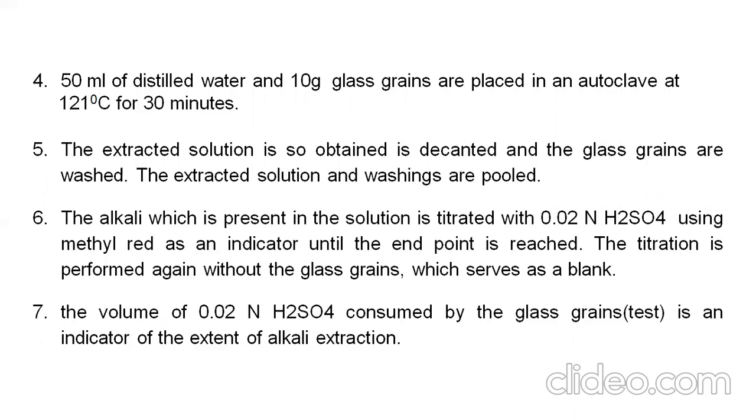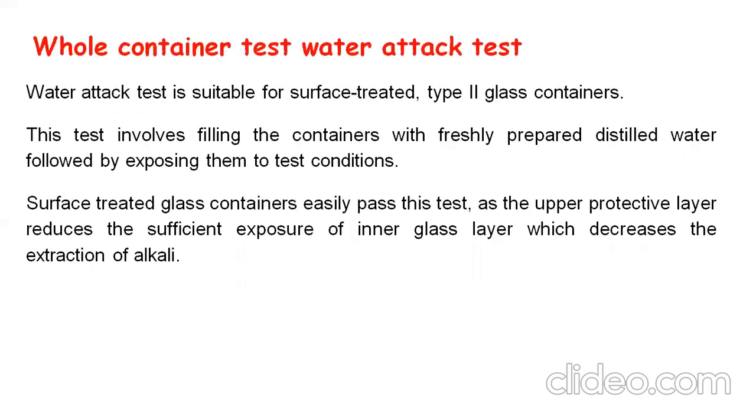The titration is performed again without the glass grains, which serves as a blank. The volume of 0.02 normal H2SO4 consumed by the glass grains, that is the test sample, is an indicator of the extent of alkali extraction. Whole container test or water attack test.